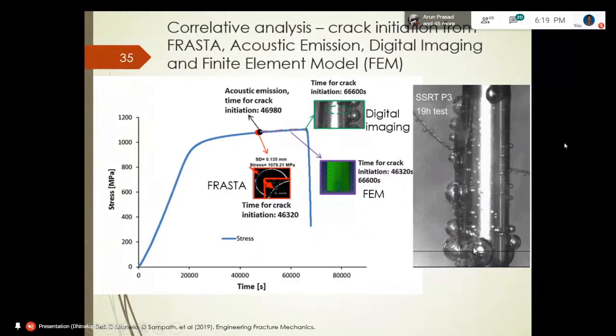And then you can see the hydrogen bubbles generating on the surface. Not all hydrogen produced on the surface gets into the material. Only a small fraction of it gets in. But still, that's very virulent to cause the damage. We have this finite element simulation as well, but it is also off by some factor. But I think the most important one, the experimental validation, is from acoustic emission, which validates the findings